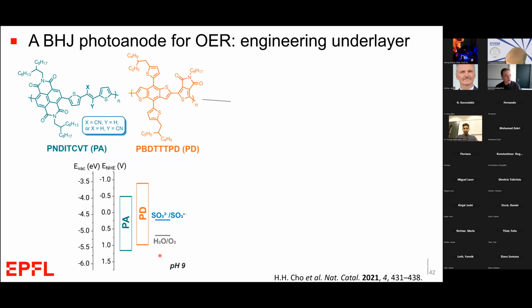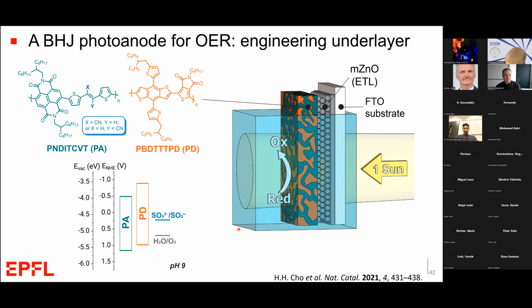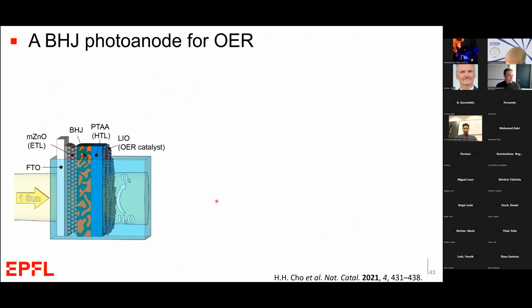And we had to play some tricks to get this to work. For example, using a mesoporous zinc oxide electron transport underlayer helped to improve the stability. I won't go into that, but you can look at the results that were published recently. And secondly, applying this PTAA overlayer, which really helps to quickly extract the holes to reduce the hole accumulation in the bulk heterojunction, which proved detrimental to the stability.